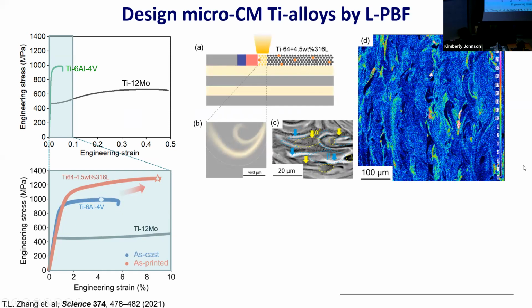So if you look at additive manufacturing, if you use just one type of alloy powder, you're going to create a chemically homogeneous melt pool. But if you use two different types of alloy powders, right, so this is Ti-6Al-4V versus stainless steel, which contains a lot of beta stabilizers, nickel, iron, and others. This is just showing you the EDS map of how the iron content is distributed in the individual melt pools, multi-layers. You see how they have this spatial concentration modulation of the iron content in this laser powder bed build.